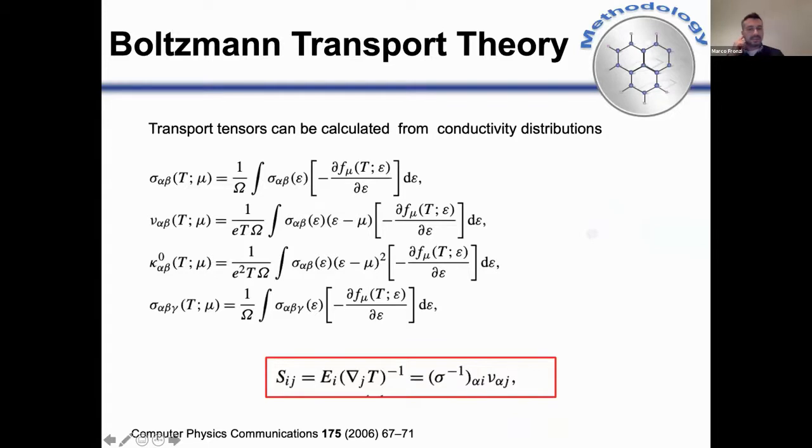Yes, we can derive all these tensors that appear in the Boltzmann transport theory that I just showed you within the density functional theory. So we do density functional theory, we apply Boltzmann theory, and we extract and calculate the Seebeck coefficient.